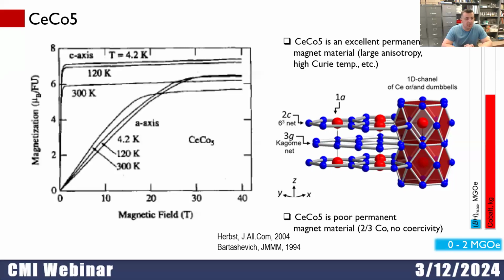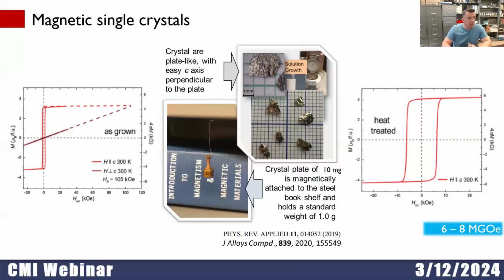It's a layered crystal structure with interesting one-dimensional channels where you have nominally cationic big atoms, large atoms, and smaller atoms, transition metal atoms. They are spread throughout the network, nominally anionic. And this is a very interesting feature of this crystal structure because there is a possibility for magnetization boost in this crystal structure. Sometimes in those one-dimensional channels, there is a possibility to introduce transition metals. So basically, you can shift your composition and increase the magnetization. So this is kind of a flexible crystal structure.